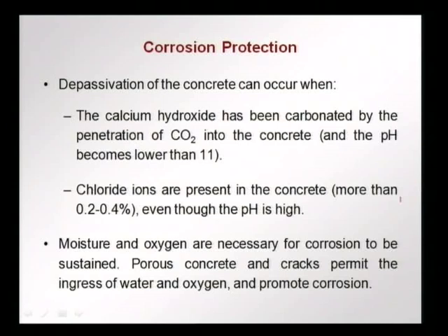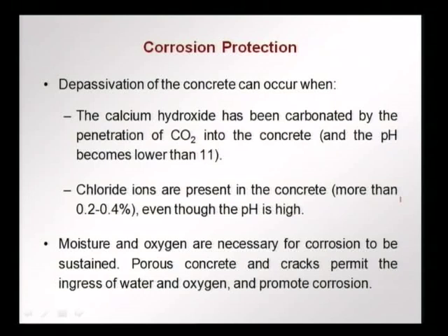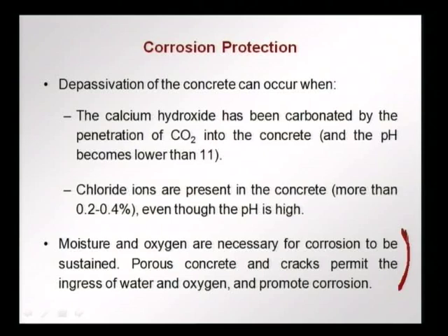Depassivation occurs mainly under two conditions: carbonation causes the pH to drop below 11 (potentially as low as 8), and chloride ions entering from salts in the environment — even at high pH, if chlorides exceed 0.2–0.4% of the concrete mass, depassivation of the steel oxide layer occurs and corrosion follows. Moisture and oxygen are necessary for corrosion; therefore we should avoid porous concrete and cracks, which permit ingress of water and oxygen and promote corrosion.